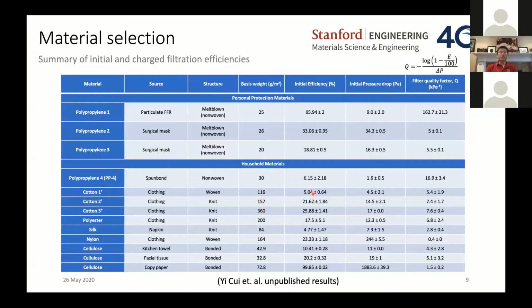Filtration efficiency ranging from 5 to 26%. Air pressure drop, 5 to about 17 Pa. You look at the quality factor, they are similar, 5 to 7 also. So looking at this quality factor 5, 7, this is a pretty good number. Indeed, cotton can be used to make a reasonable quality of facial mask.